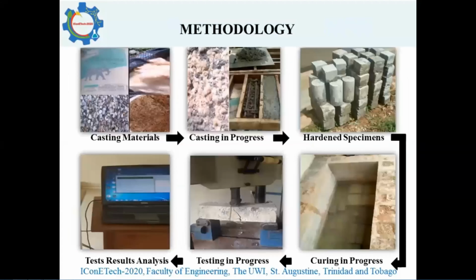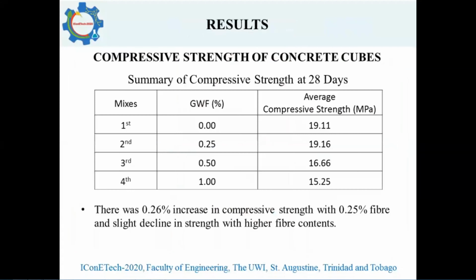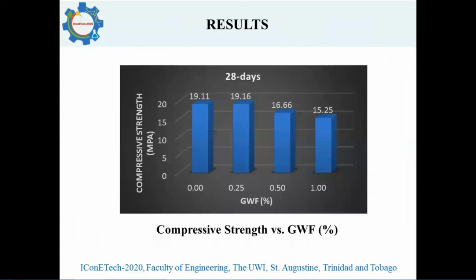Analysis and results. Compressive strength of concrete cubes. The table shows the 4 mixes with their corresponding percentage glass wool fiber and the average compressive strength obtained in MPa. This is a bar chart of the compressive strength versus percentage glass wool fiber. From the bar chart, there was a 0.26% increase in compressive strength with 0.25% fiber and slight decline in strength with higher fiber content.